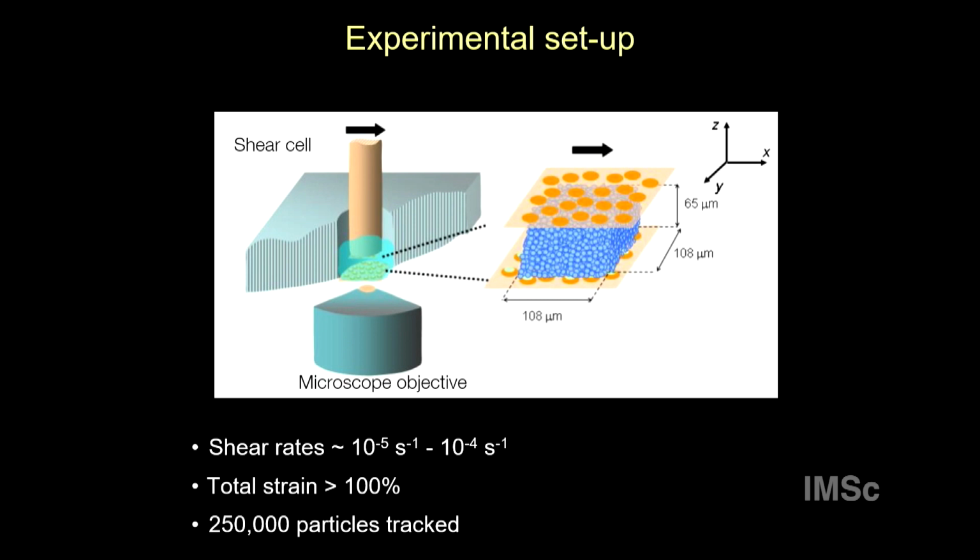And the yellow circles are stuck particles? Yeah, exactly. That is to prevent crystallization at the boundaries. It's not a monodisperse system. It has 7% polydispersity to prevent crystallization.